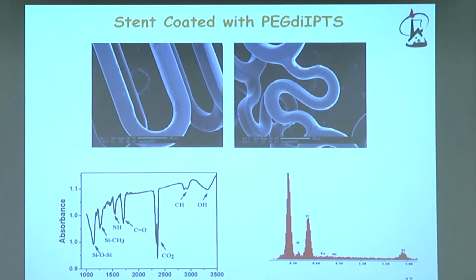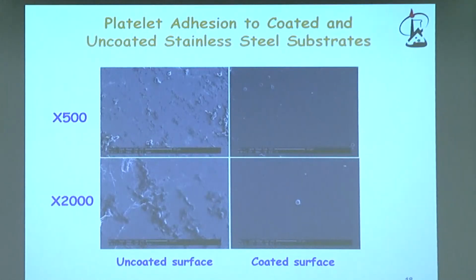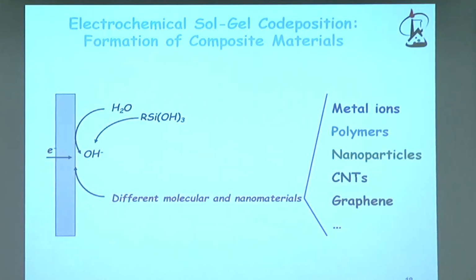And then once you expose it to red cells, you can see this is an uncoated surface, this is a coated stent, and you can see that on the non-coated stent, actually the red cells proliferate and they grow and so on. On the coated surface, almost nothing grows. So this is one example. What else you can do with that, with this indirect deposition?